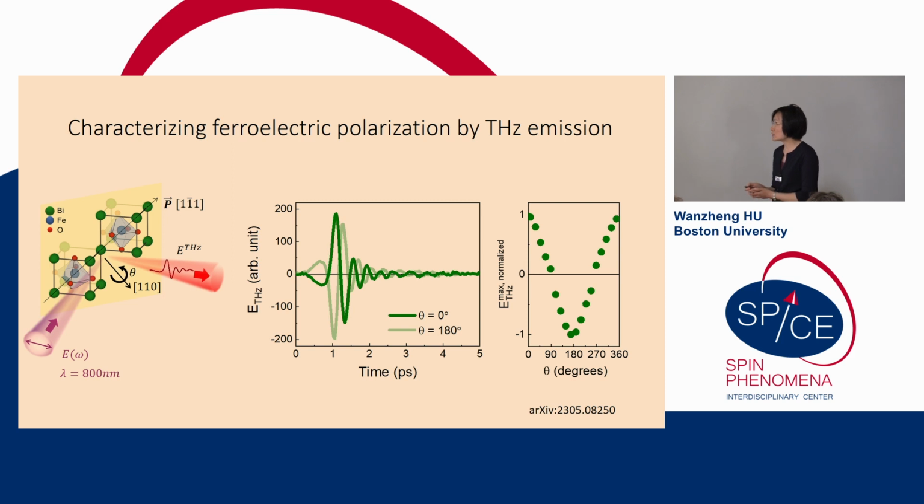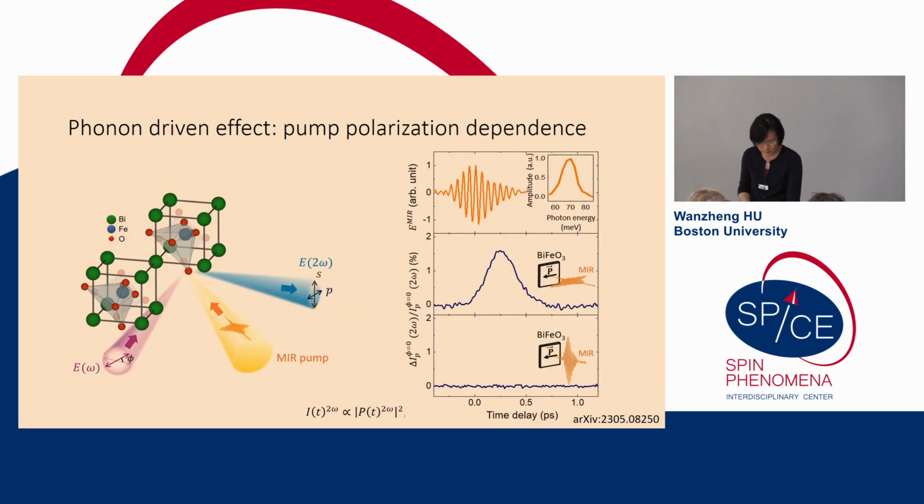But in order to carefully orient the sample for the mid-IR pumping, we need to characterize the exact orientation of the ferroelectric polarization. Here you see, for several rotational angles of the sample, the generated terahertz magnitude, and it indeed follows a very well-defined angle dependence, which says our material is mostly a single domain. Okay, so then in the pump-probe measurement, we shine the mid-IR pump.